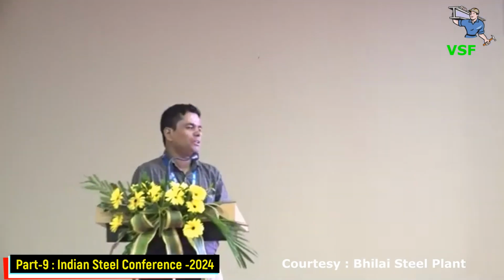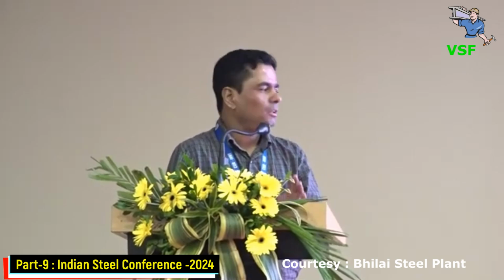But the problem is that when we are dealing with lump ores, this process is okay, but when we are dealing with fine ores, which are a good resource of low grade ores in terms of slimes, tailings, and previously discarded ores, which are primarily in the form of fine particles, what happens? We face the problem of over reduction. Instead of the material stopping at magnetite, it over-reduces to wustite and metallic iron, causing a significant loss of Fe in those forms.